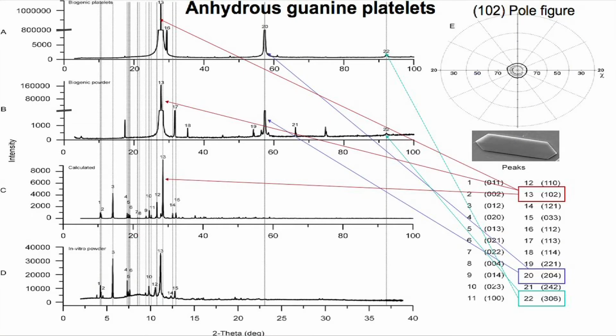So the first thing that we had to do is to identify the structure, and in fact the structure corresponds to the one that would be calculated in a powder diagram from the structure of anhydrous guanine. But look what happens, and that's quite interesting. Although this reflection is the dominant one, in the fish this reflection is so much more developed than all the others that it was clear that there is a phenomenon of orientation.